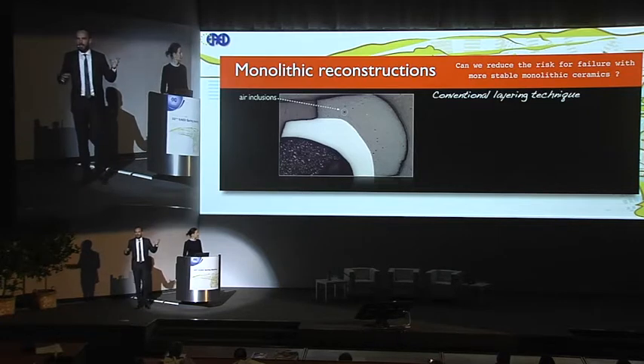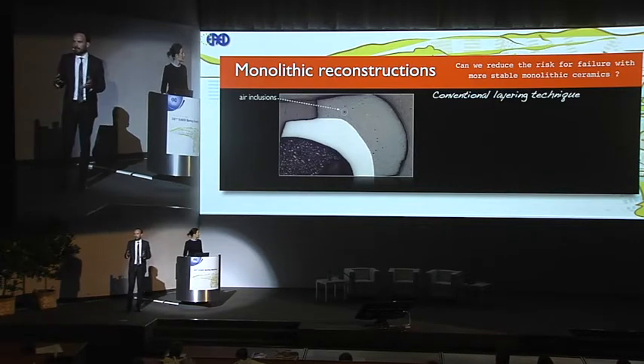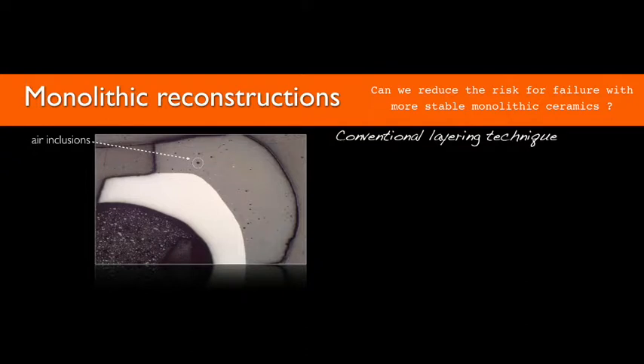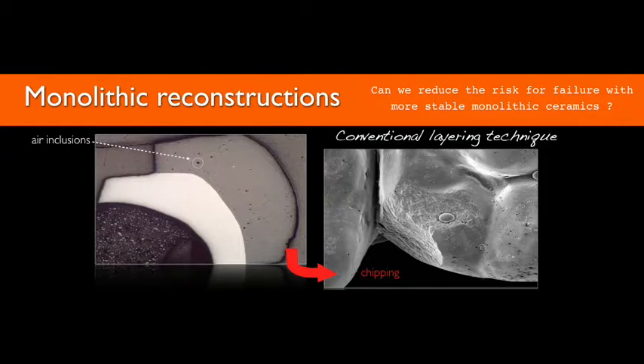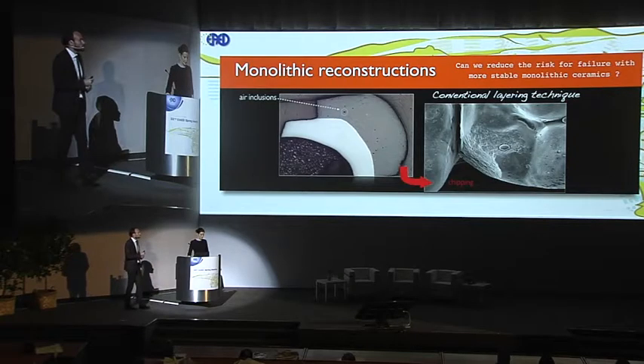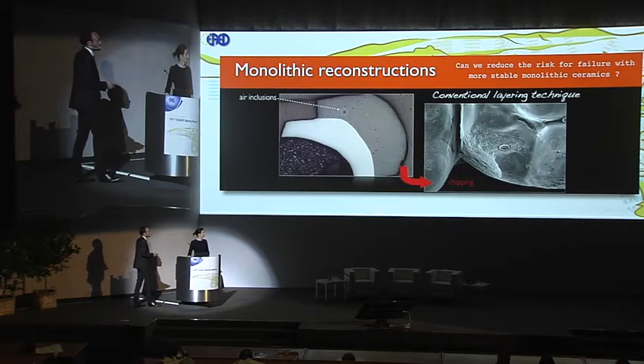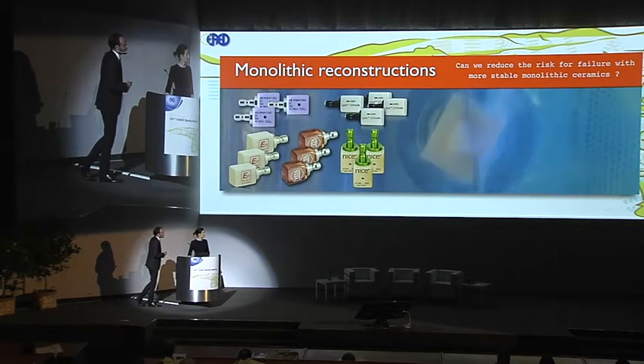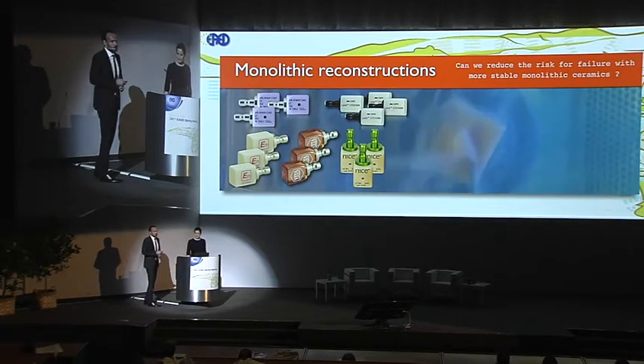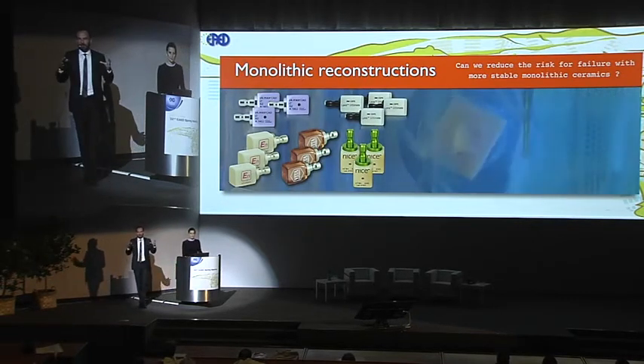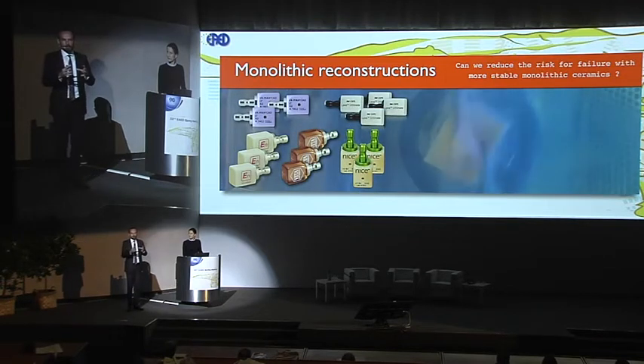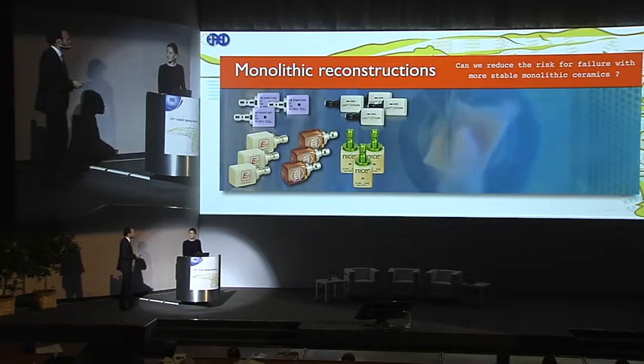And clearly this is associated to the way of production that we are handling here. Basically, aligning these products, the powder with the liquids, baking it into the oven, no matter how good the vacuum is, we will end up with these small air inclusions beside other factors like occlusal wear, roughnesses, parafunction, pH index, or the moisture level. We will end up with the weakness of the material and therefore with the chipping. So clearly what we could think of is just ask the industry to provide us with a very perfect dense material, and we chop it down to create our monolithic reconstruction.